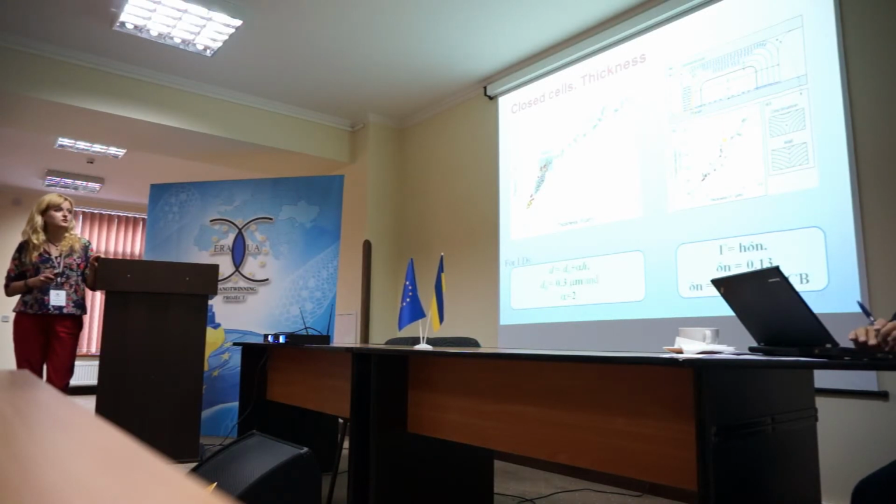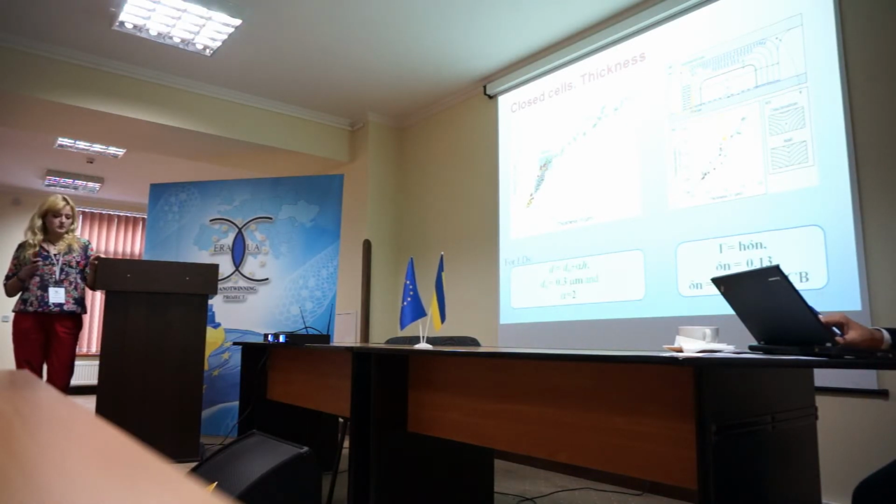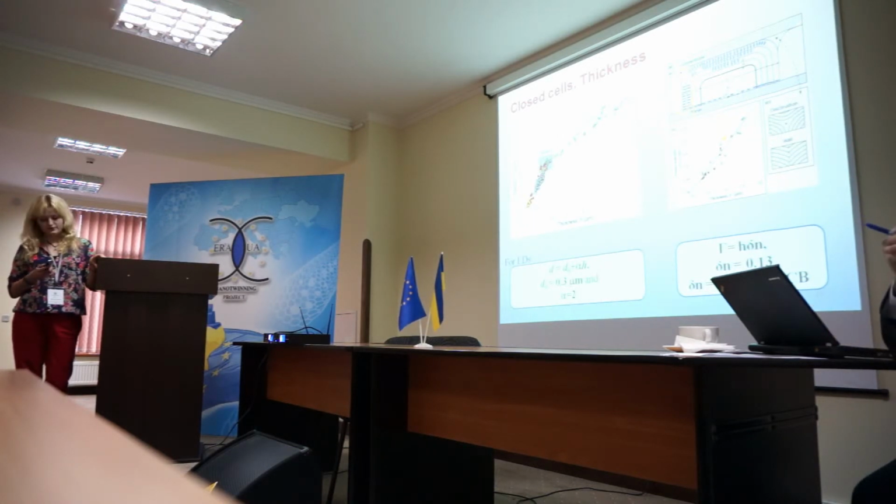Also, this model shows that close to the homeotropic substrate, smectic layers have to be bent almost 90 degrees, which means that probably locally the anchoring conditions vanished, and there may be some topological defects present. We expect disclinations close to the defect walls and inside the defect pores.